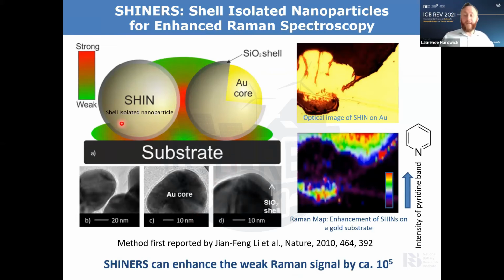As I said, we can put this on any electrode surface, and so this is an example of putting these particles on a piece of planar gold. You can see the coffee ring from putting these particles down. These are all our nanoparticles on the gold surface, and then we add pyridine onto the gold, and the pyridine adsorbs onto the gold surface. But with conventional Raman, the particular band for the adsorption of pyridine, you can't detect it. It's too weak. This is the Raman map of these particles on the surface. Dark is where there's no enhancement, and in the red we have very strong signal from the pyridine. So we can observe the adsorbed pyridine on the gold, and that matches very well to where the location of these particles are.